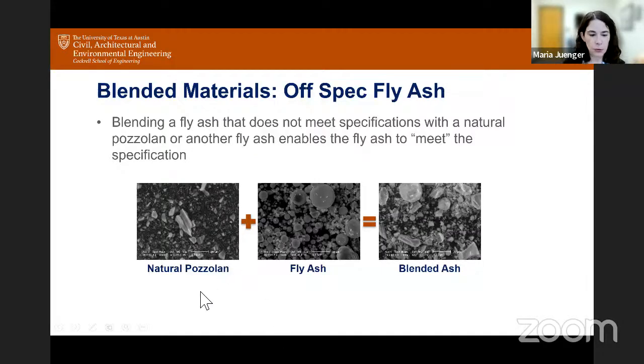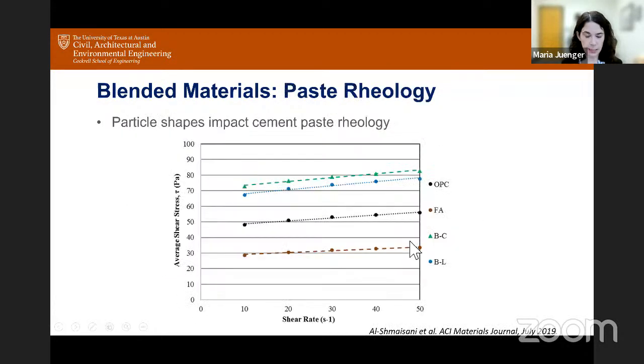One example is if you take a natural pozzolan and you blend it with a fly ash, you can get a blended pozzolan ash material. And so this is an excellent opportunity to optimize and engineer your blends for performance by taking advantage of available resources. So these are SEM images of a natural pozzolan, a fly ash, and this particular blended material, which you can see has rounded particles and angular particles mixed together.